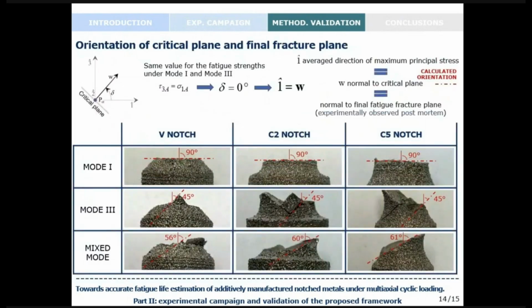Then, finally, here we can see the comparison between the orientation of the critical plane calculated by means of the methodology and the final fracture plane that is experimentally observed post-mortem on the specimens tested. So for mode 1 loading, we can see in red the calculated orientation. For mode 1 loading, we have a critical plane perpendicular to the longitudinal axis of the specimens. This plane becomes oriented at 45 degrees with the longitudinal axis of the specimens in case of mode 3 loadings, and these values are the same for all the notch